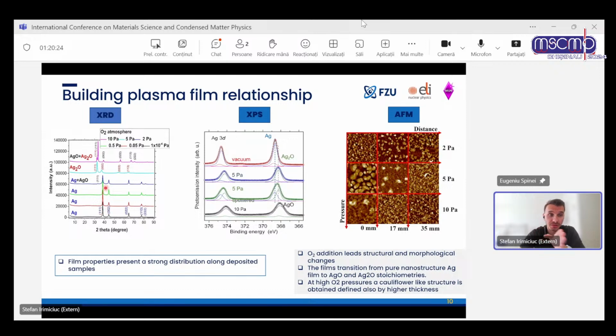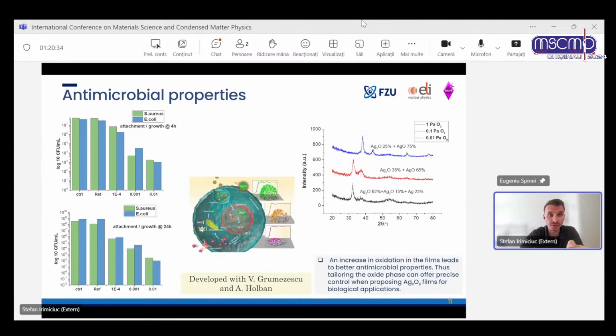So by controlling the oxygen in the chamber, we can change the oxide state of the silver, we can change the morphology, and then we can put all that to good use for antimicrobial properties. And we can improve these antimicrobial properties by controlling the oxide phase in the film. It started from the process, started from the deposition, understanding, producing the films, and then towards the application. And now this is a robust technology. This is something that we can scale up, we can transfer, because we understand everything about the production.